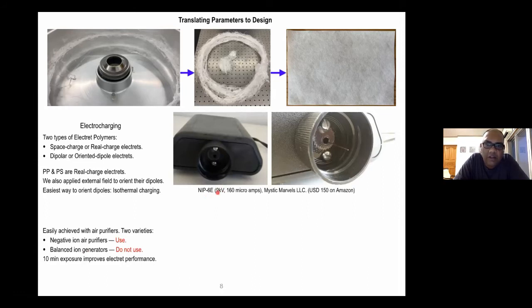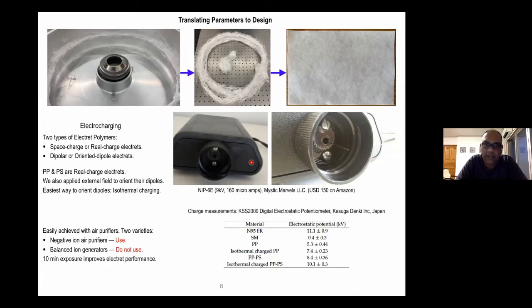It operates at 9 kilovolts, and here is a blown-up image of the end where I hold the polymer fabric to be electrocharged. You have one electrode coming out and the other electrode inside. As the air is being blown, the negative ions are basically getting onto the electrocharged layer. That is the principle of isothermal charging, and we were holding it for about 10 minutes. We did trial and error for 1 minute, 2 minutes, up to 10-minute durations, and measured the amount of static charge. First, let me show you the results we saw.